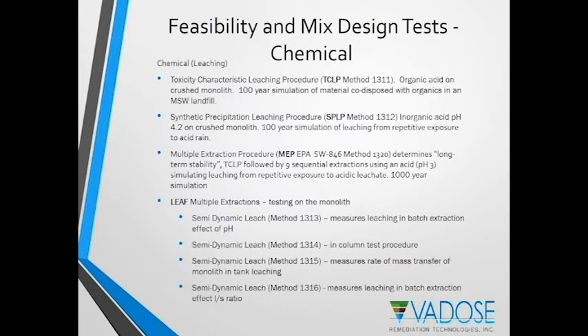Now, further to leaching testing for chemical analysis of the effectiveness of these different solidification or stabilization methods, I've mentioned the TCLP. Essentially, the toxic characteristic leaching procedure is intended to evaluate whether the waste is considered toxic or hazardous or non-hazardous, depending upon that criterion. This involves using organic acid and essentially percolating it through crushed monolith. So it's intended to be a 100-year simulation of materials that had been co-disposed with organics in a municipal solid waste landfill.